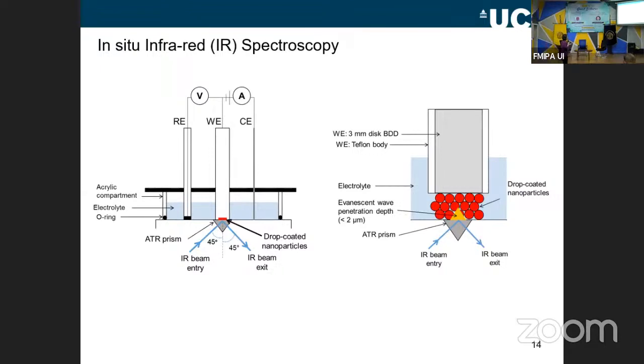And how this works is that we have here a prism, and the infrared beam comes into the prism. It undergoes total internal reflection at the surface of the prism and then comes out again. But some of the energy can penetrate a little bit above the prism. And if there's a sample there, it will absorb the infrared, and you're able to measure the vibrational or infrared spectrum of whatever is just above the prism. So that's how the technique works.